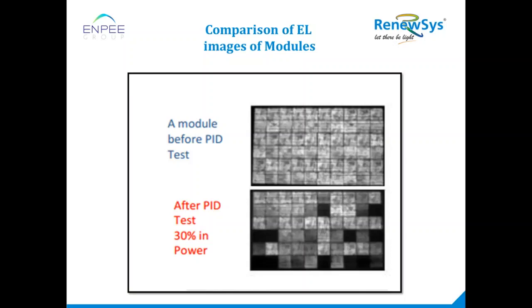See, when I was speaking about the presentation, I said that typically when the solar industry started, the effect of PID was not identified. Why it was not identified is because in those days the system voltages were at 600 volts. At 600 volts, you won't find any issue. Even in smaller installations, like a smaller home where we typically connect around 5-10 modules, this effect is not going to be there. So the moment you touch 1000 volts or beyond, PID comes into the picture. In terms of voltage, I can say 600 is more or less safe, but starting from 1000 onwards, you have to be very careful. On 1500 volts, which is the current trend, you have to be even more careful.